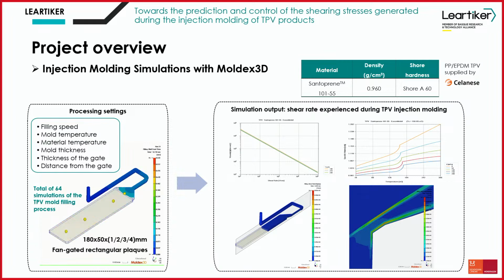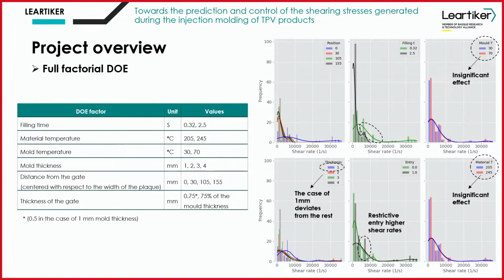So we did in total 64 simulations of the TPV mold filling process, and as an output we analyzed how all these process parameters affect the shear rate in the different positions and for different plates with different thicknesses from 1 up to 4 millimeters. So once we did these simulations, we performed a full factorial design of experiments to analyze how the different process parameters may influence the shear rate, and at the end, as we showed in a previous slide, the microstructure and the final properties that we can have.